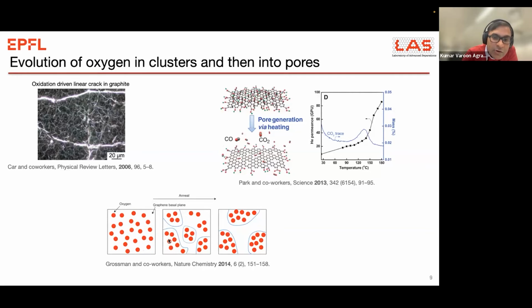In graphene oxide, what people started to see is that there is a phase separation of the material itself, in a sense that there are hydrophilic oxygen domains and hydrophobic pristine domains. It has also been shown that once you heat this material, you release CO2 and incorporate porosity. But the exact precision of how this chemistry happens, how to control it, because remember, for gas separation, you need to have a precise pore size distribution in graphene. So this is what we were chasing.